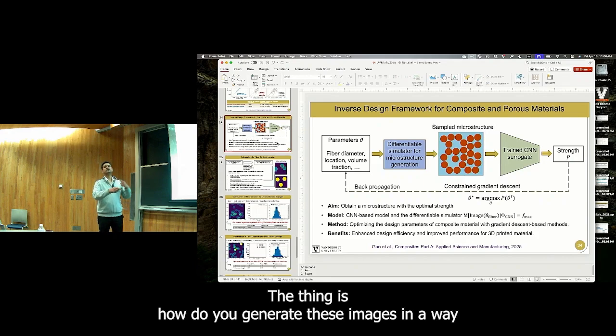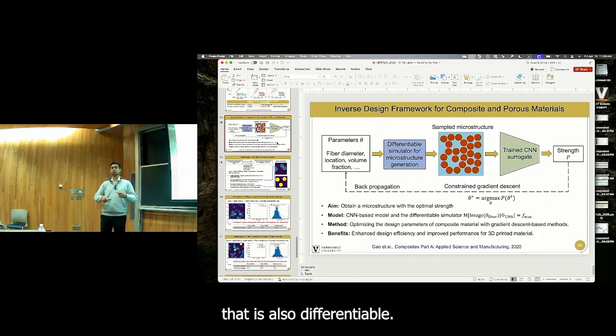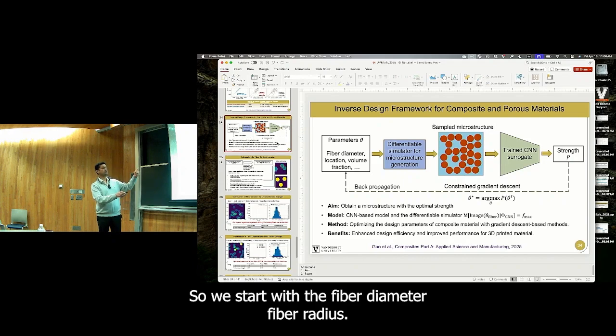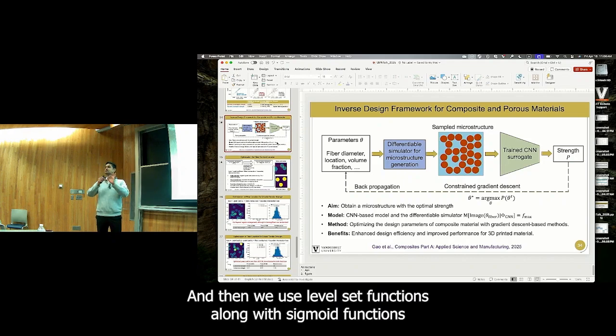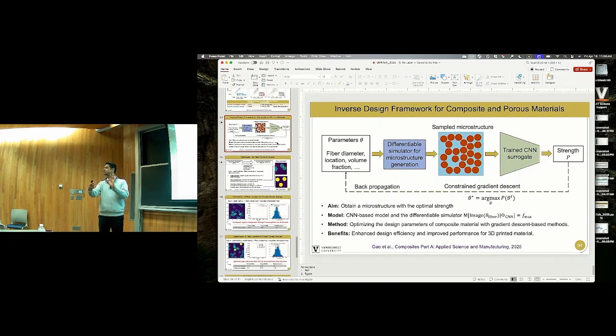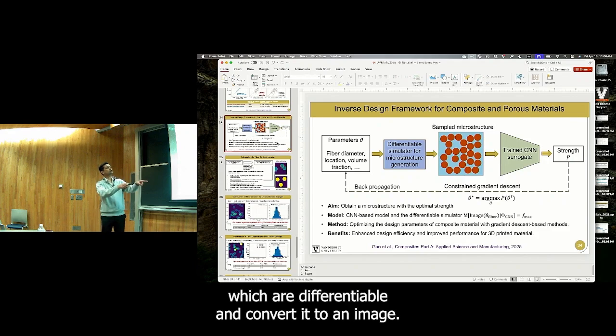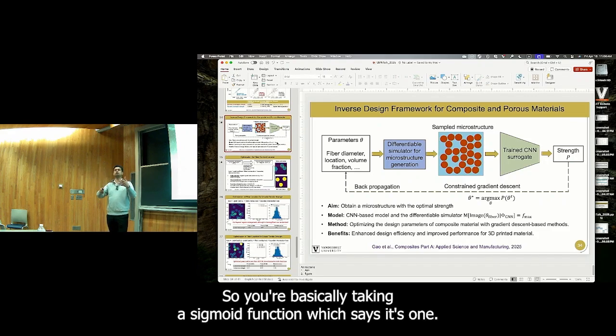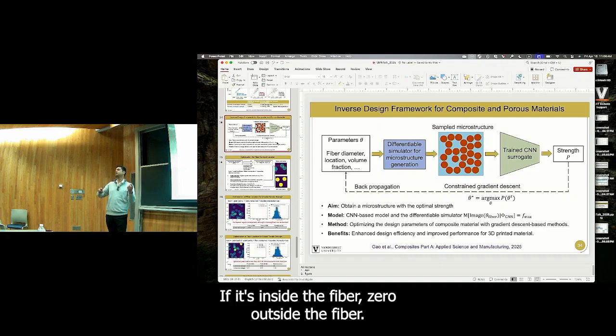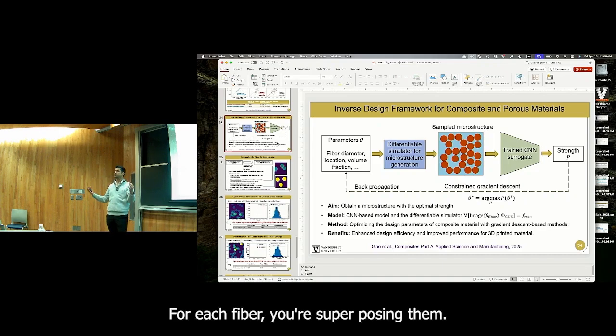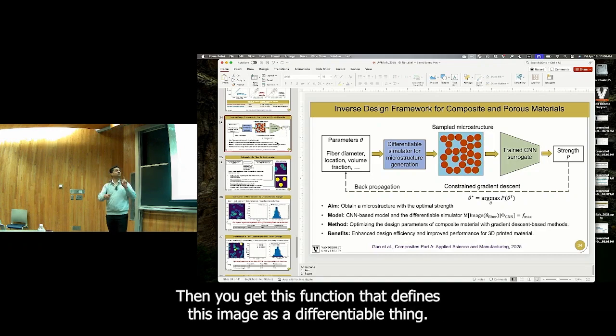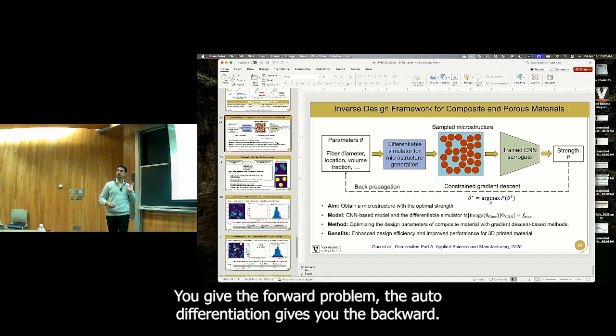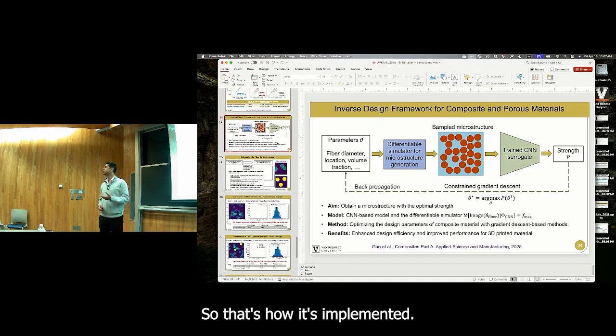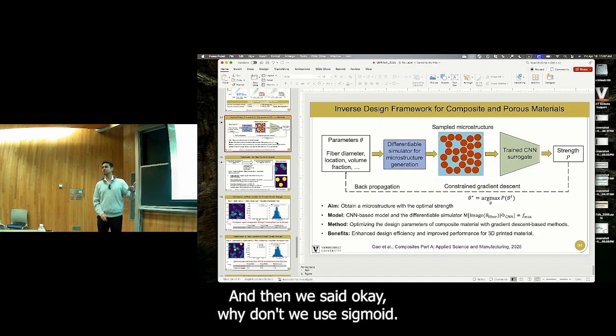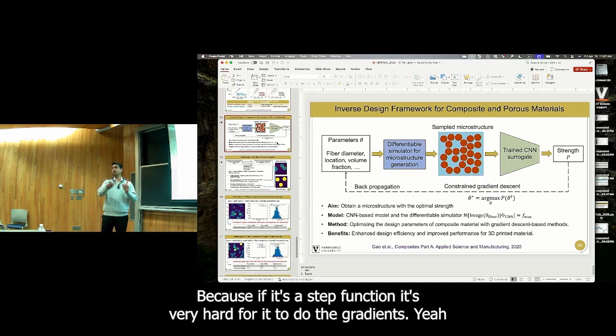The thing is, how do you generate these images in a way that is also differentiable? So we start with the fiber diameter, fiber radius, and then we use level set functions along with sigmoid functions, which are differentiable, and convert it to an image. So you're basically taking a sigmoid function which says it's 1 if it's inside the fiber, 0 outside the fiber. For each fiber, you're superposing them, and then you get this function that defines this image as a differentiable thing. You give the forward problem, the auto differentiation gives you the backward. So that's how it's implemented. Thank you. Great question. We struggled with that initially, and then we said, okay, why don't we use sigmoids? Because if it's a step function, it's very hard for it to do the gradients.